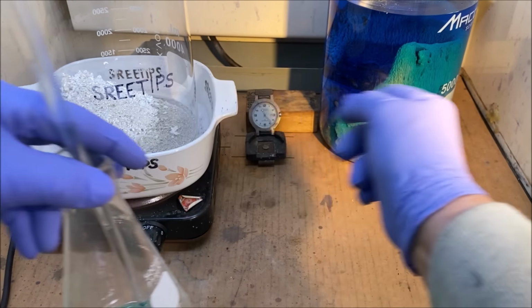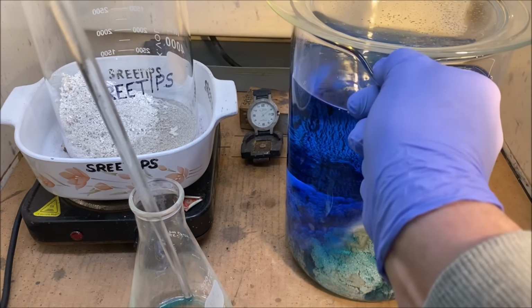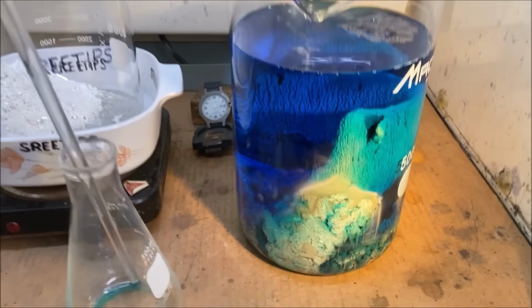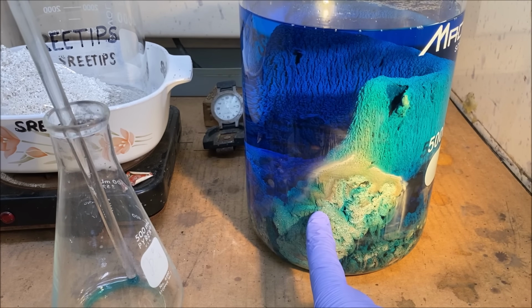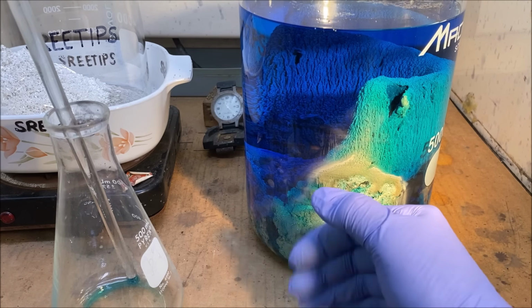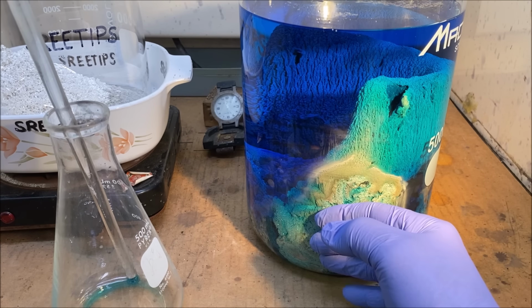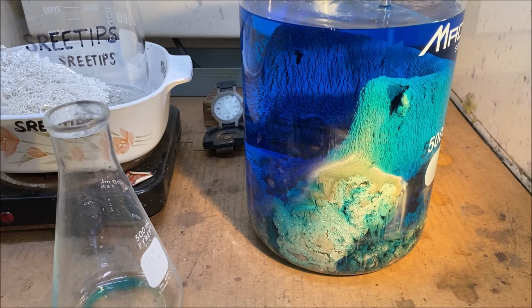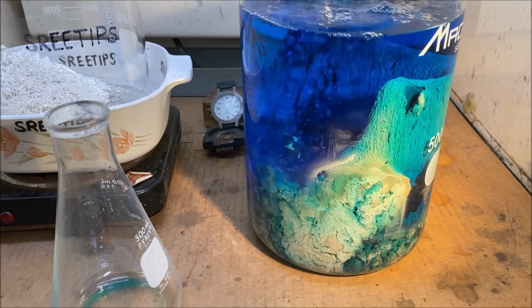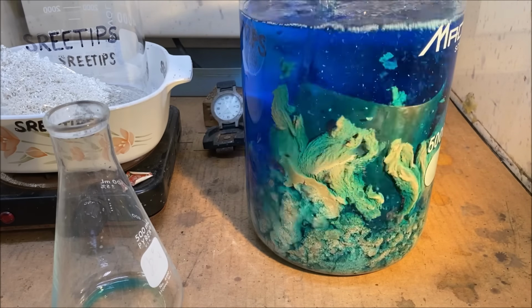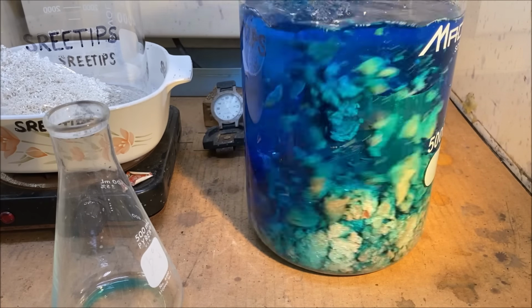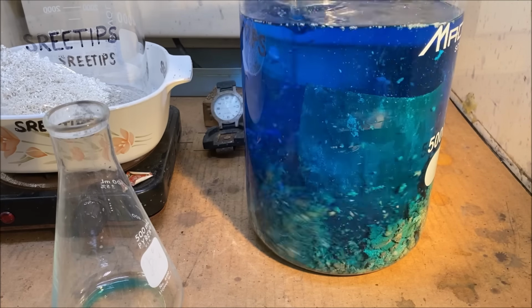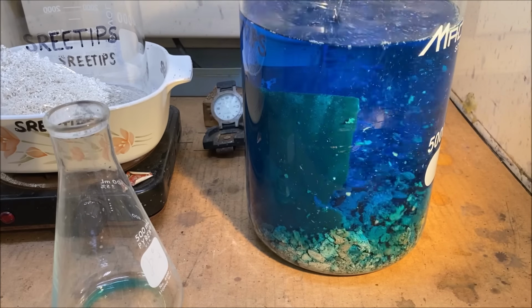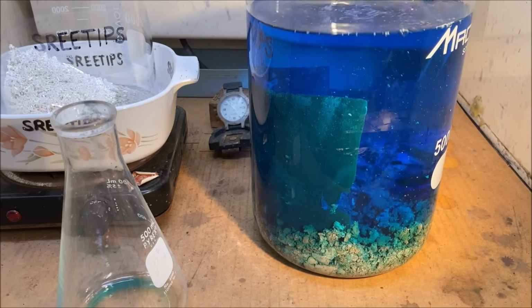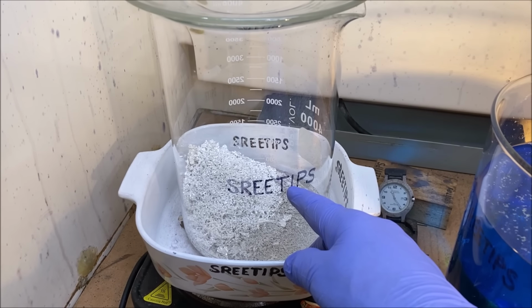Before I get going with this, I wanted to show you this is the cement silver from a previous silver cell run, and this is the electrolyte from my 3.5 liter silver cell. After the electrolyte has served its purpose, which is to transfer the silver ions from the anode filter basket through the electrolyte and down into the cathode, where those silver ions plate out on the inside of the cathode. This is a piece of copper in here, and none of the silver that I use up here will get used up.